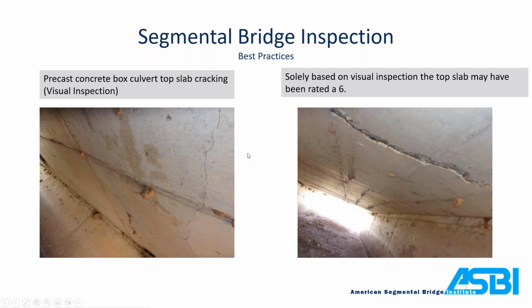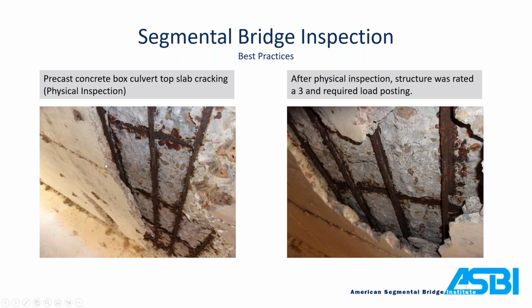Well, if you get inside this thing and bang on it, that concrete is actually really bad and falls off. And you can see here, you're probably pretty close to 50% section loss on your transverse top mat steel for this box culvert. This ended up requiring a load rating and posting, which resulted in a condition rating of a 3, a critical finding. So this just kind of demonstrates how important it is to bang around those cracks and determine the validity of the concrete. What condition is that concrete in? How stable is it? Is there anything going on underneath there that's causing that crack associated with the steel?